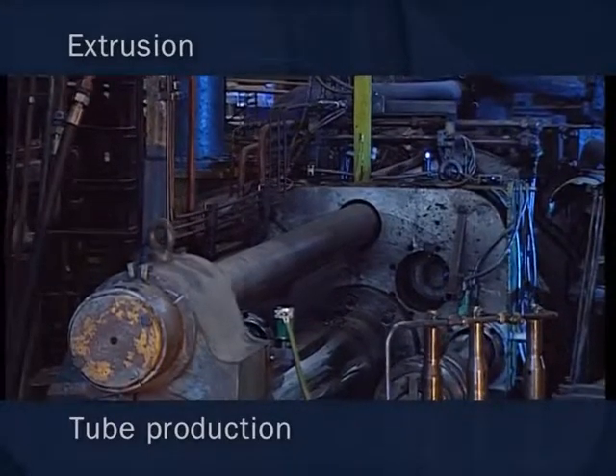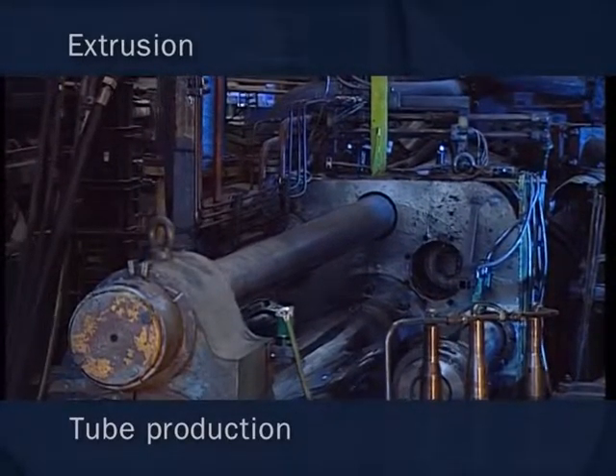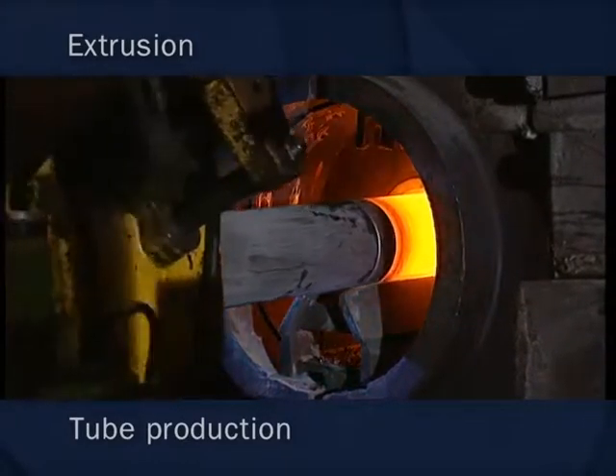3,300 tons force the material to go through a gap between extrusion die and extrusion mandrel. During the process, the outer diameter is reduced to the extrusion die's dimension. The extrusion mandrel defines the inner diameter. The tube length and geometry are precisely calculated beforehand, exactly meeting the customer's requirements.